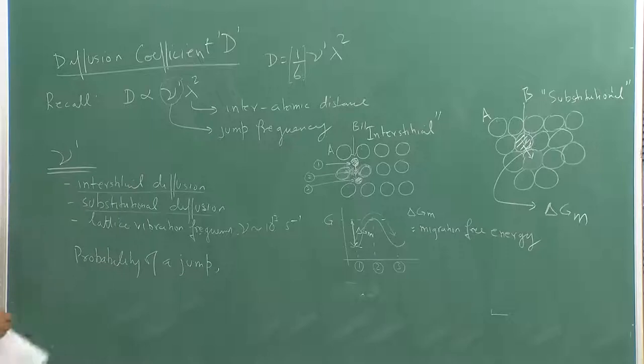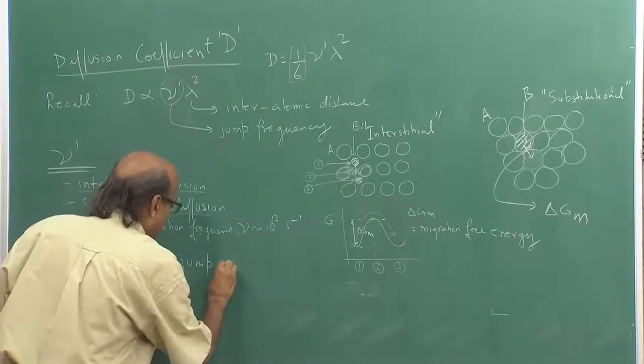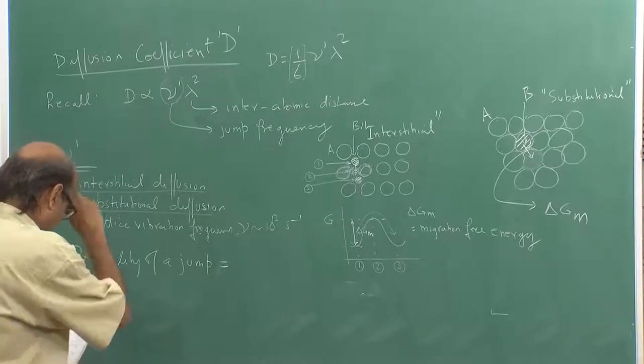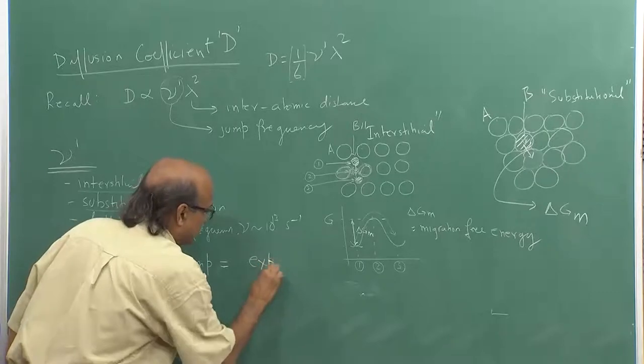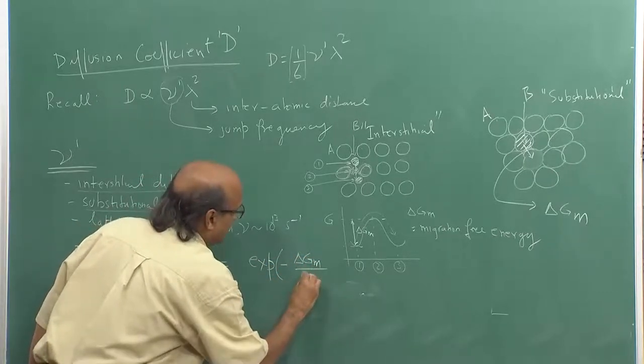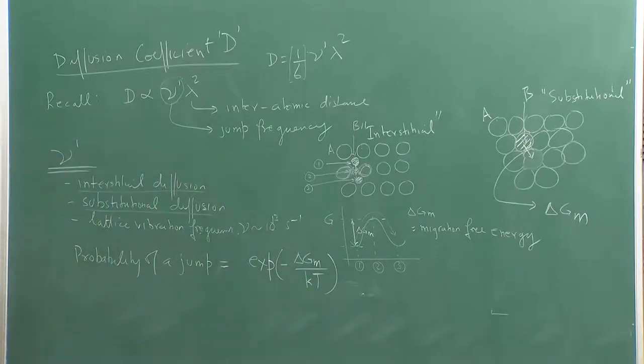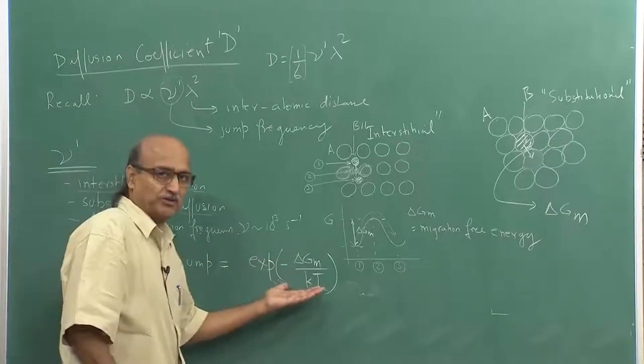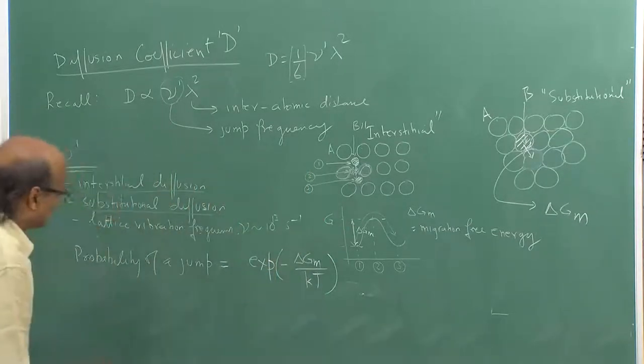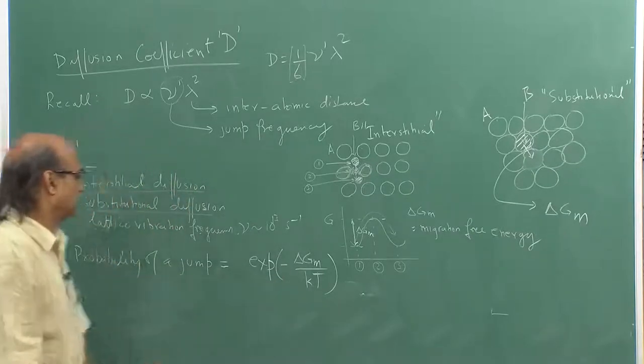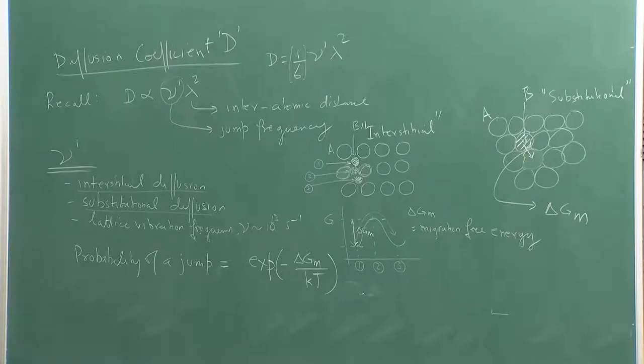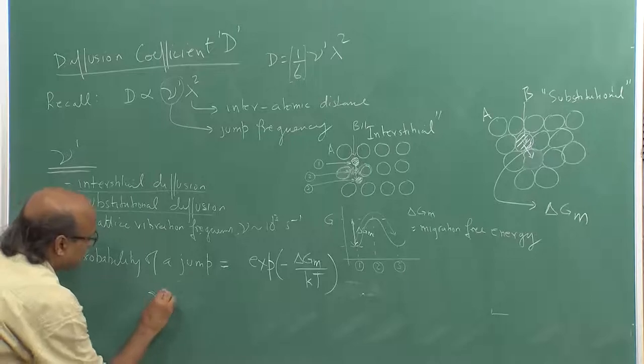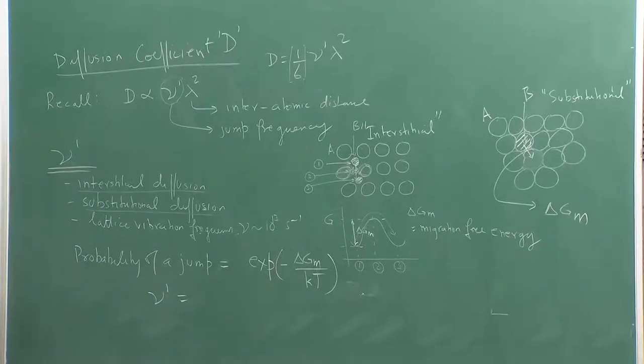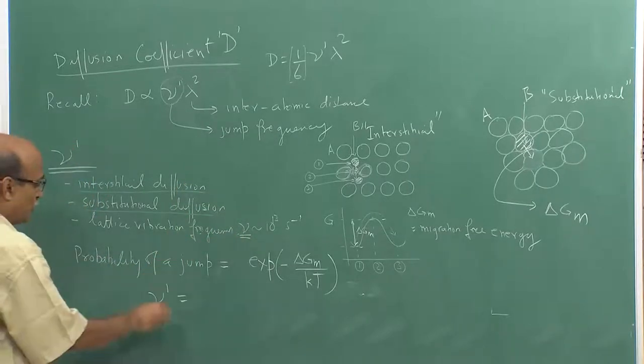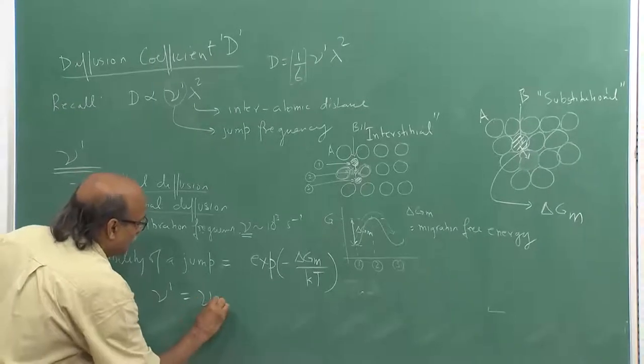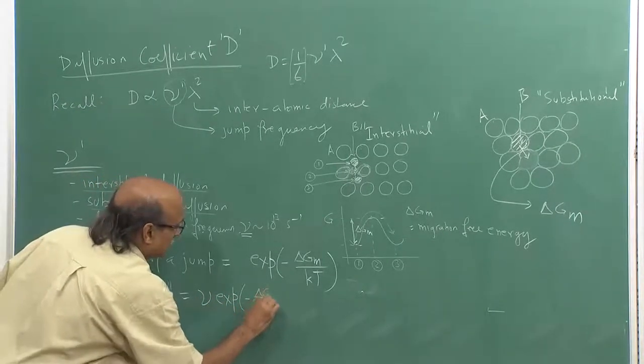So, the probability of a jump would be equal to exponential minus delta Gm divided by kT, just like we had seen in the case of nucleation also, or jump of atoms across the interface. It is a similar kind of expression that is going to be related to the probability of a jump. And hence, what is the frequency of jumps then? Well, atoms are vibrating with a frequency of nu, and hence nu prime, the jump frequency, is equal to nu times exponential minus delta Gm upon kT.